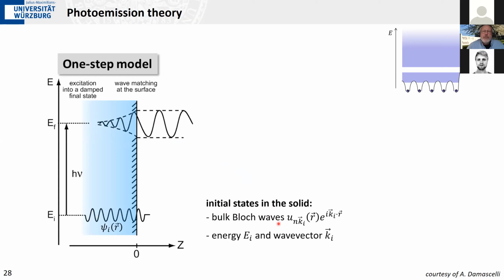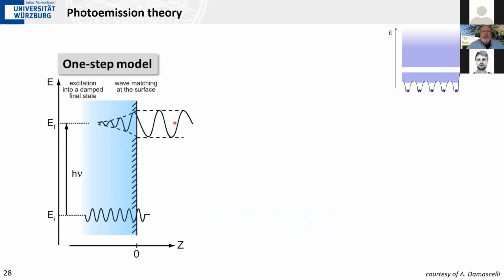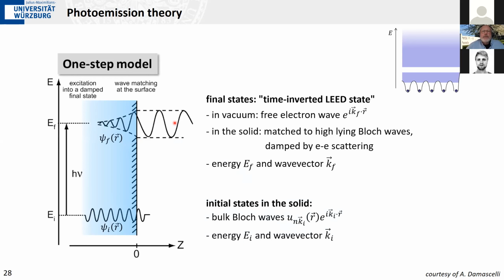That's just the normal Bloch wave that we have in our solid, characterized by its initial state energy and its wave vector Ki. And then we excite this into the state here that I've drawn up here. And we call these final states time inverted LEED states, because they are really the time reversal version of the states that you create when you do a LEED experiment, a low energy electron diffraction experiment, where you shoot an electron beam at the surface and then look at the reflection, and part of it will transmit into the interior, and now we reverse this in time.